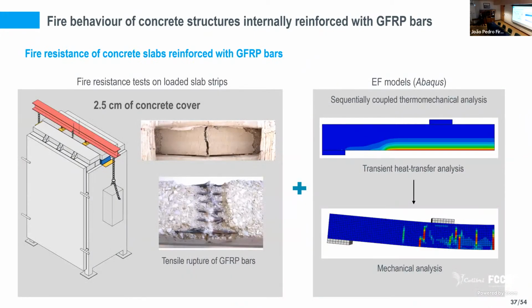Then at a different scale of analysis, we proceeded with the fire resistance tests of concrete slabs using a test setup similar to the one I showed you before, where we adopted a very thin concrete cover, much thinner than the one recommended by the Canadian code. We wanted to demonstrate that it would be possible to adopt very thin concrete covers for these bars and still have a good fire resistance, and we combined the experimental campaign with numerical simulations.